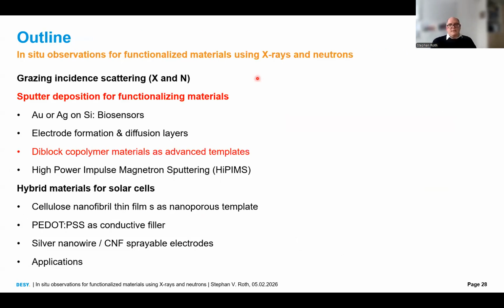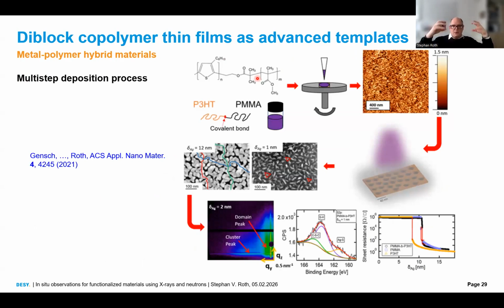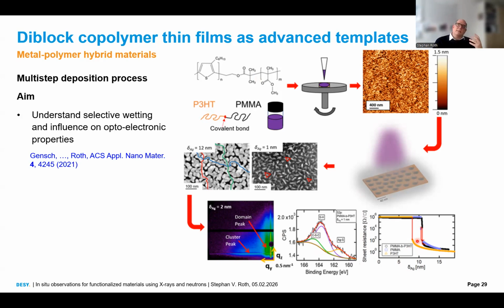So in the next step, I would like to make this a little bit more complicated. We go away from our pure layers and we use diblock copolymer materials. These materials are 2 polymers which are covalently bound. We spin coat our layers. Typically they have 20 nanometer to 100 nanometer thickness. We put our sputter chamber into the beamline. We deposit our metal. We measure GISAXS. We can measure ex-situ XPS and SEM, and we can measure the conductivity. And this becomes now important, that we are really able to deduce, and I will prove it to you, the electrical conductivity onset in our systems. And why we are doing this is that we want to understand selective wetting and influence on optoelectronic properties.